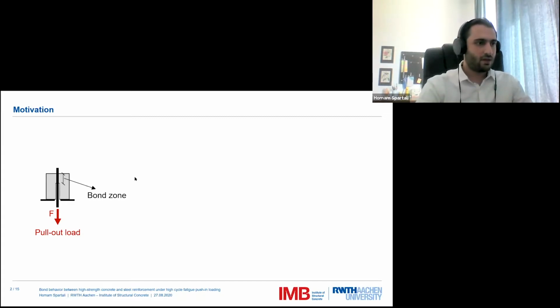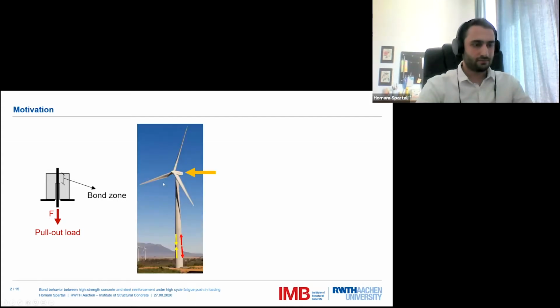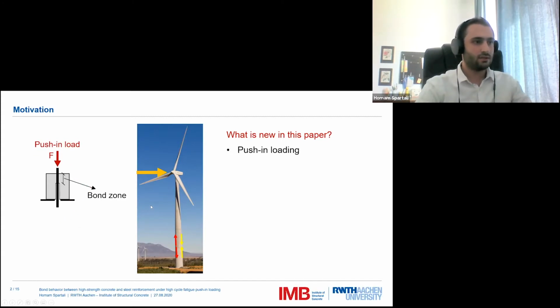However, because of the demand for renewable energy, structures that may be subject to alternating loading have been developed, like wind turbines. In these structures, this alternating loading can trigger compression stresses as well as tension stresses in the same reinforcement rebars. That means that both cases, the pull-out case and the push-in load state, need to be investigated, because in the push-in case, we may see different bond behavior or bond stress profile along the bond zone.